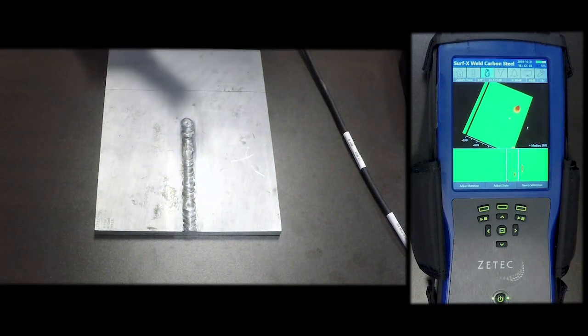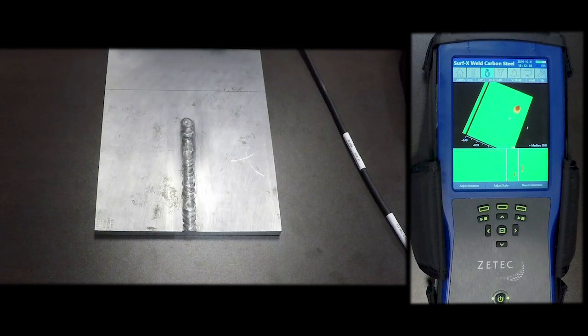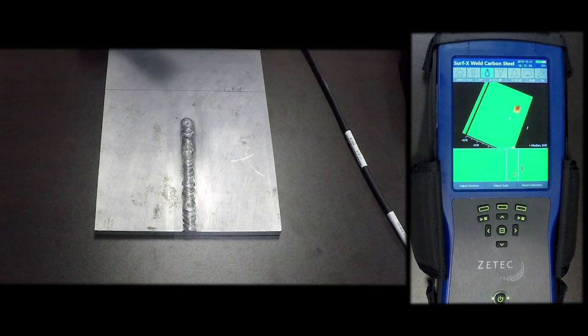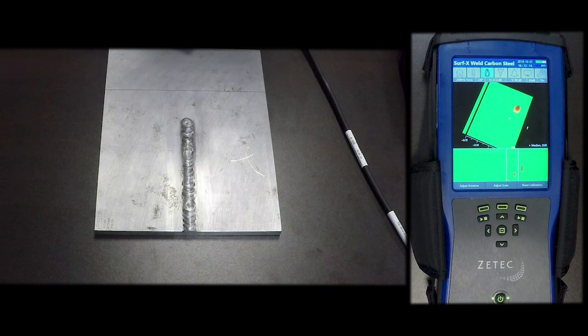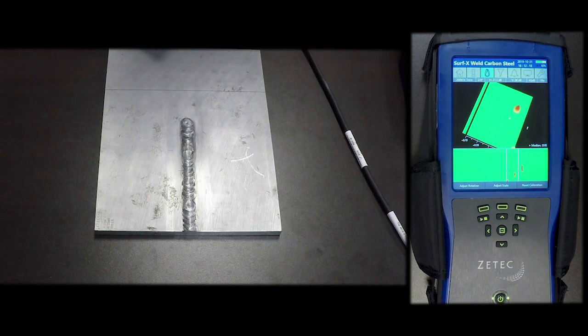So that's how you would perform this inspection on a weld. You do it in three passes and you can record up to 10 meters or 30 feet or 60 seconds per scan. Then you can just do those multiple data files if you need to do a really long weld seam and get the full coverage.